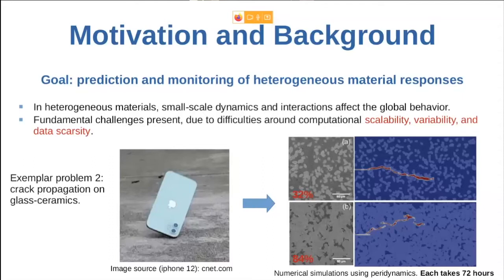It's a material called glass ceramics. Glass ceramics is one type of glass which contains a volume fraction of randomly distributed crystal grains in a glassy matrix. Here, what I'm showing is two examples of the lab-observed microstructure of the glass ceramics. The light green represents the crystal grains, and the dark gray represents the glassy matrix.